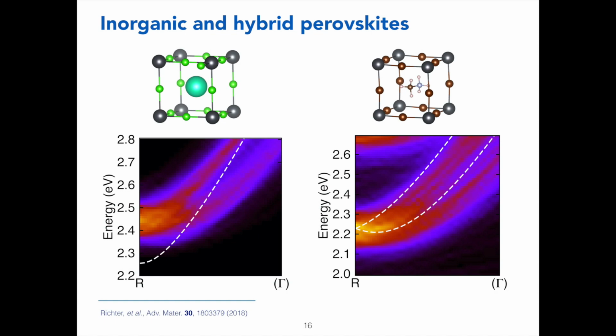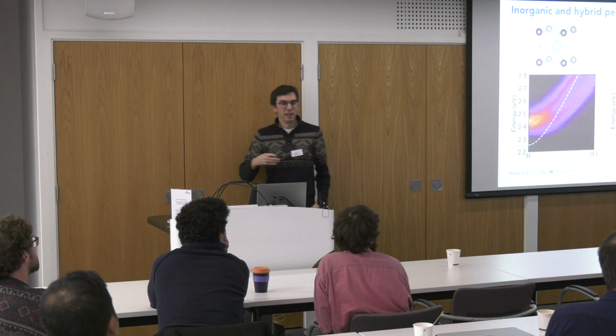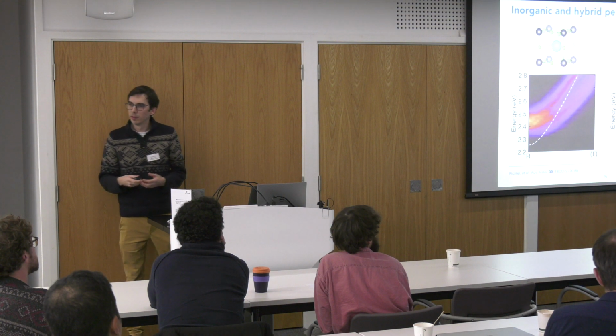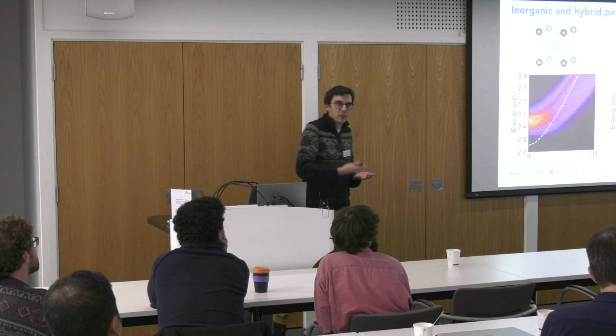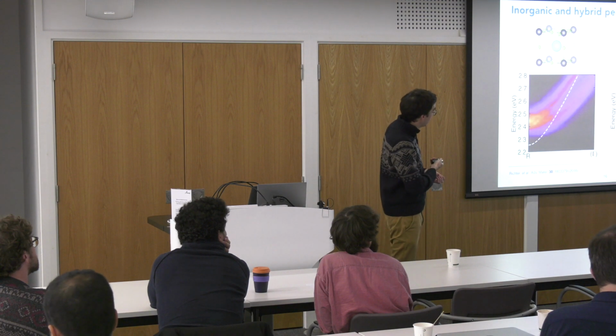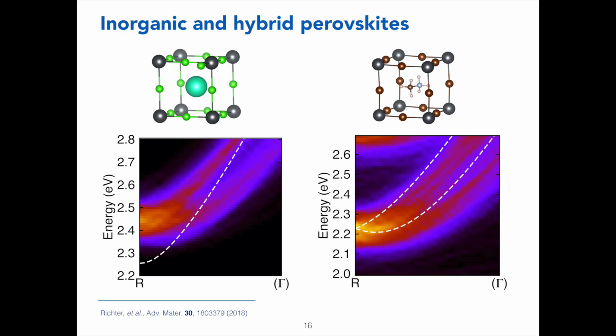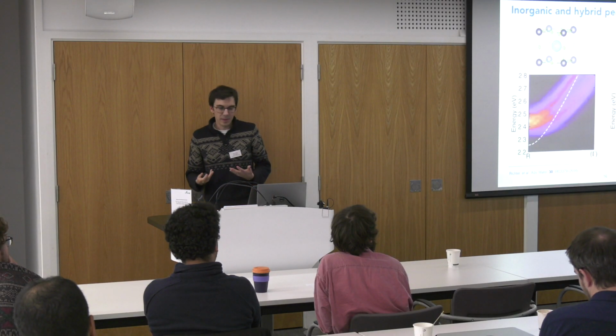So if we start with the inorganic material, what used to be a doubly degenerate band now splits into two branches. And this is, in fact, a type of dynamic Rashba effect, where the dynamic disorder locally breaks inversion symmetry and induces this spin splitting due to spin-orbit coupling. And the same happens in the hybrid case. But interestingly, the energy scale of the vibration is such that it washes out completely this slight indirect band gap that arose at the static lattice level. And that shows how dynamic disorder makes two seemingly very different materials behave in the same manner.